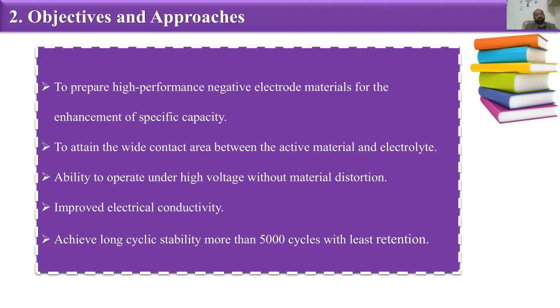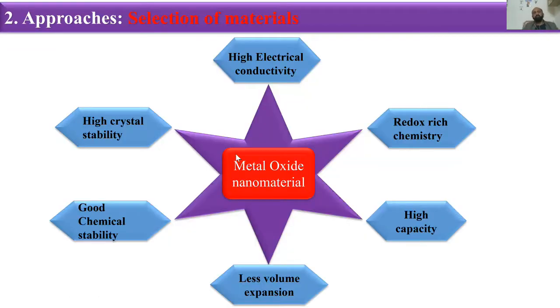We have prepared the supercapacitors for high specific capacity, and we want to enhance the contact area between the active material and the electrolyte. We also want to improve the electrical conductivity, and improve the number of cycles for better retention of the materials. So we have used metal oxide nanomaterials for our system, because they have properties like high electrical conductivity, high crystal stability, good chemical stability, and less volume expansion. They have redox chemistry and high capacity.